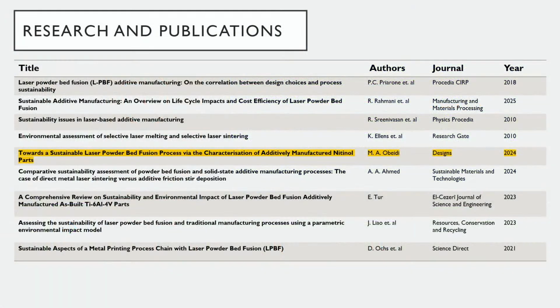So that's why I selected nickel titanium, because these two metals, I'm melting them here using the laser. So in order to melt titanium, some of the nickel is vaporized and sublimated already. And that will change the properties: from 50% atomic percentage, it is a shape memory. If the nickel is 51%, that's superelastic. And it can be not biocompatible anymore if titanium changes its phase from alpha to beta. So that's why I selected nickel titanium.